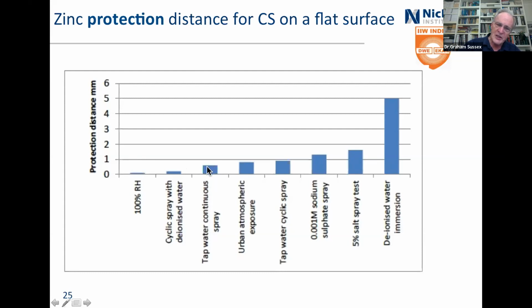If you're putting tap water continuously on it, then the tap water is going to be a bit more conductive, depends where you are, but it's going to spread a bit further. If you're looking at urban atmospheric, this is basically going to depend on whether you're down beside the sea or out in the middle of the desert or in a standard urban environment. The tap water cyclic spray is basically compared to that, and there's not a lot of difference in those two, but you can get building up concentration, and so you get a bit of conductivity across the surface. Sodium sulfate spray, seawater spray, 5%, or continuous immersion. This is with deionized water, so it's not a great conductor, but it's still something that means that you could go 5 millimeters or so out.